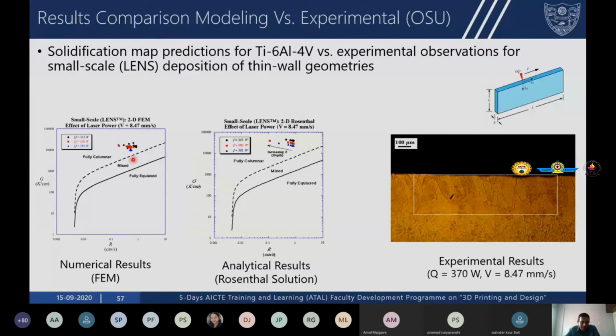So this is a solidification map where we are plotting G, thermal gradient, on the y-axis, and R, which is the solidification growth rate, on the x-axis. So this is from the finite element model results. And now you can see that the map is divided into 3 regions. The first region is fully columnar, then you have mixed and fully equiaxed. So this is for different powers at a constant scan speed.